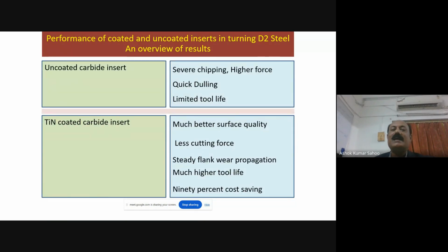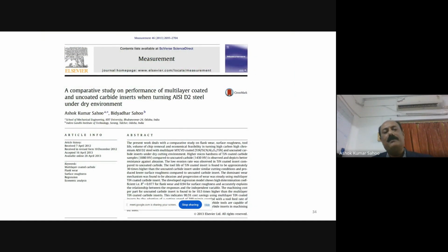So in conclusion of this case study, we observed that the uncoated carbide insert induces severe chipping, higher cutting forces, quick dulling of the cutting edges, and very low tool life as compared to the TiN coated carbide insert, which gives higher surface quality, less cutting force, steady flank wear progression to achieve the tool life, so tool life is higher, and 90% cost saving. So this is the benefit of utilizing the coated carbide insert, to get higher machinability, higher tool life and less cost during machining of hardened steel. This paper has been published in the journal Measurement, Elsevier.